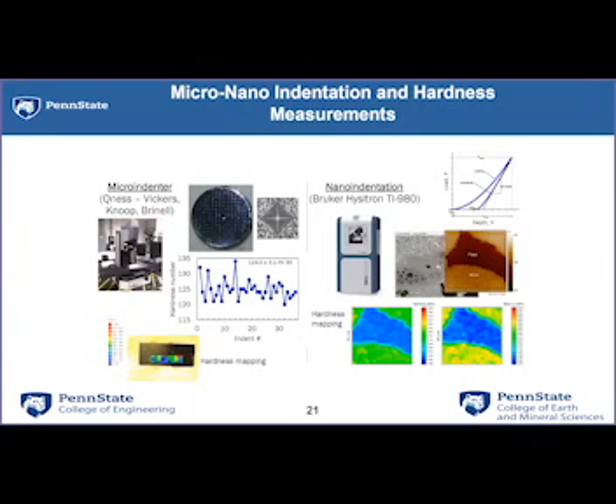Micro and nano indenters, this has gone a long way too. This is a lot beyond what you might have used in school, the manual micro hardness indenter. The micro hardness indenters we use basically map out entire hardness maps of surfaces. For the most part, it uses CNC type tools to lay out a map, and we can pretty quickly, over the course of an hour or two, take a look and characterize the hardness across fairly large areas.